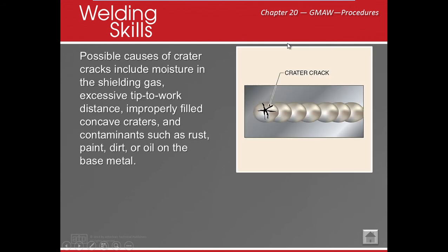Okay, so the next one, crater crack. Let me tell you that this is probably the most common crack that I see. Usually what happens is that if you do not properly fill the end of your weld and bring it up to where it needs to be, it will create a crack because it created some stresses here. We can also have problems when we have a lot of rust or dirt or just dirty base metals. Okay, it'll also cause cracks near the end. Okay, so we want to make sure that we have filled our weld all the way when we end it.